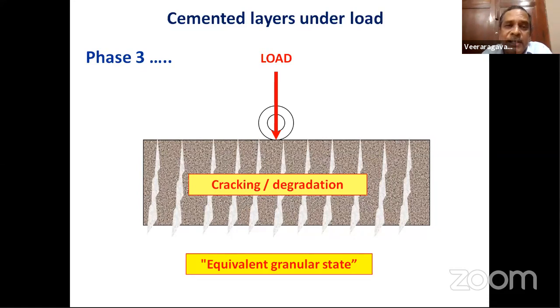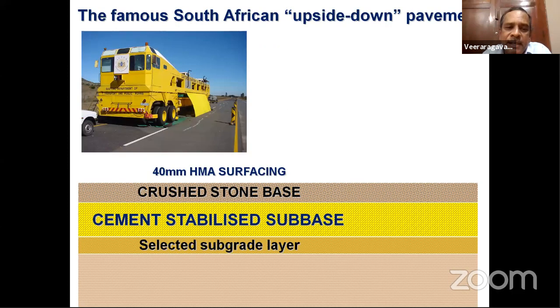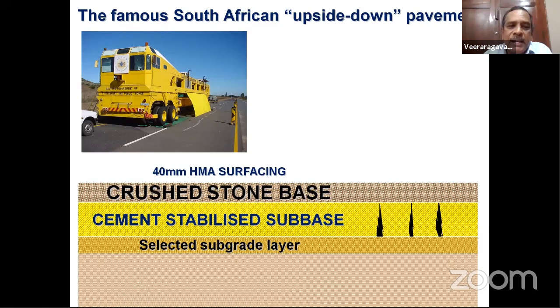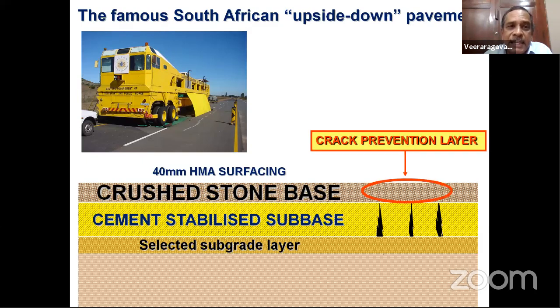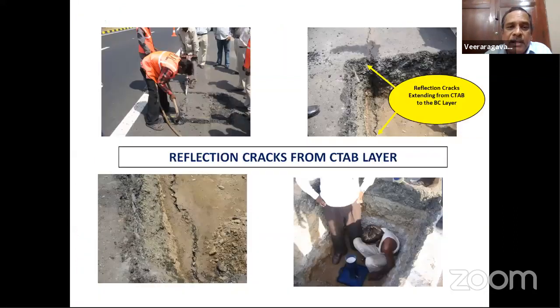So what are the issues here? When cracks occur on a cemented base, they will appear and extend to the top bituminous layer. To retard that, we have suggested a crushed stone base as a cushioning layer in between, which will retard the appearance of cracks on the top. That is its function, so that is a crack prevention layer. So this is from the, I think Mr. Jaswant Kumar is here, as he was CGM at the NHAI, he is aware of this.